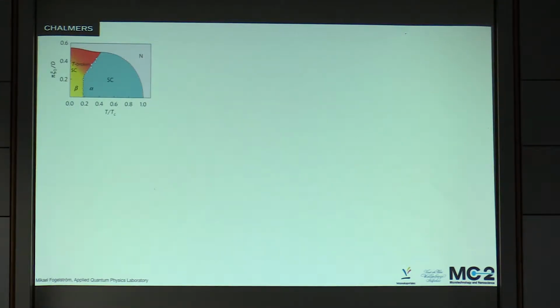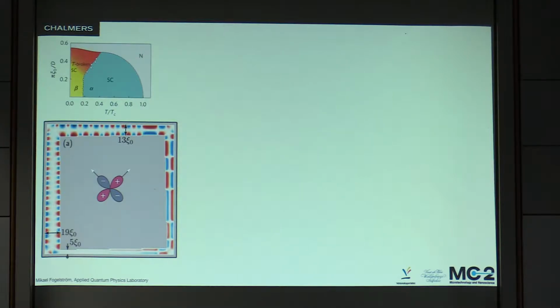Now our student Patrick started playing with the code and did some examples. We wanted to see how robust this one is. So first he made a D-wave snake. It looks like this. So he made a sort of narrow ribbon of D-wave, but it increases in width as you go by here. And what he's plotting here is not the currents, but the induced magnetic field flux that you have along the surface. And what he's mimicking is that he's going along this line. So he's starting up here with a very narrow slab. There's nothing happening. And then suddenly you get these states where you have spontaneous currents, but they are homogeneous.